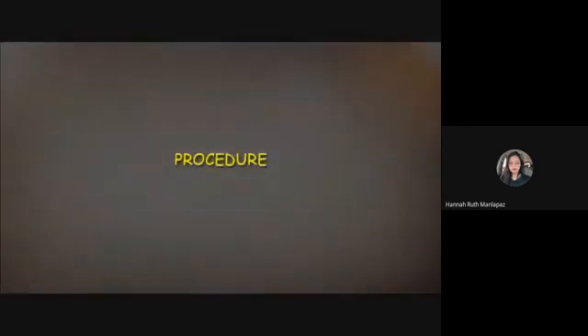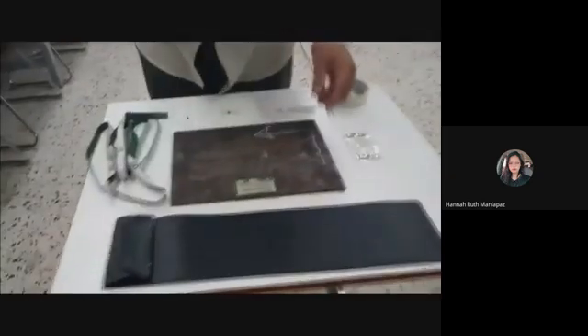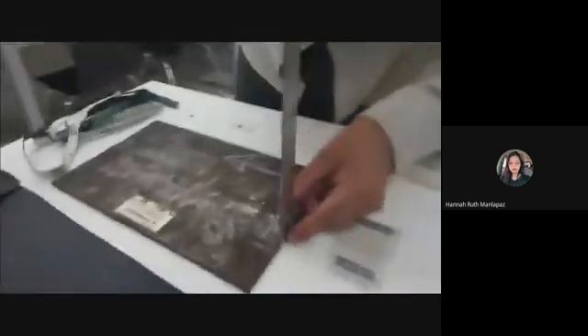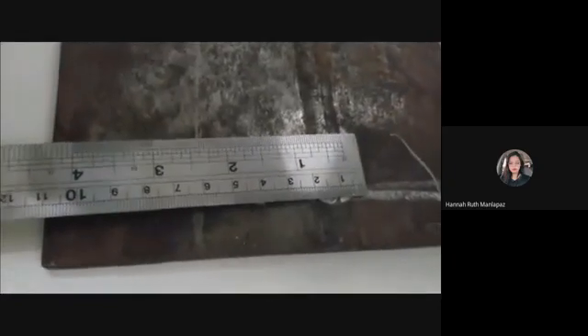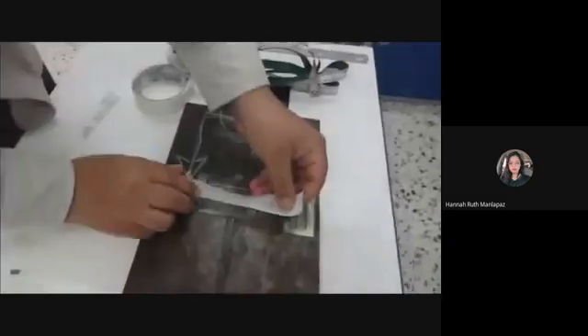The procedure is: after finishing film loading, start to perform this technique with visual inspection of the specimen. Examine the welded specimen visually and note down any surface defects. Choose the appropriate IQI type according to the sample thickness, of the same material as that of the specimen. IQI should be placed in a proper manner on the specimen, i.e. source side, with wires across the weld. Place the film underneath the plate. Place the lead letters.